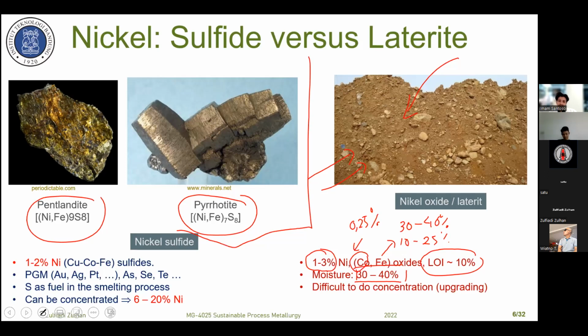Now we can say that for this type of nickel ore, it's difficult to make a concentration, to do upgrading, to increase the nickel content, for example, from 1 to 3% on the surface. We increase it to, for example, 10%. It's very difficult. It's not possible at the moment because the nickel is not free. It's always in the other minerals.